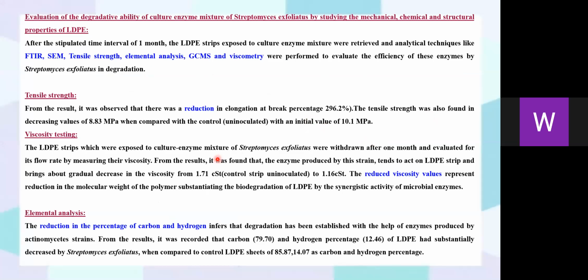Viscosity testing: LDPE strips were exposed to the culture enzyme mixture of Streptomyces exfoliatus. From the result, it was found that enzymes produced by the strain act on the LDPE strip and bring about a gradual decrease in the viscosity from 1.71 to 1.16 cSt. The reduced viscosity value represents a reduction in the molecular weight of the polymer, substantiating the biodegradation of LDPE by the synergistic activity of microbial enzymes. Elemental analysis also inferred that, with the help of enzymes produced by the actinomycete strains, there was a reduction in the percentage of carbon and hydrogen. It was recorded.